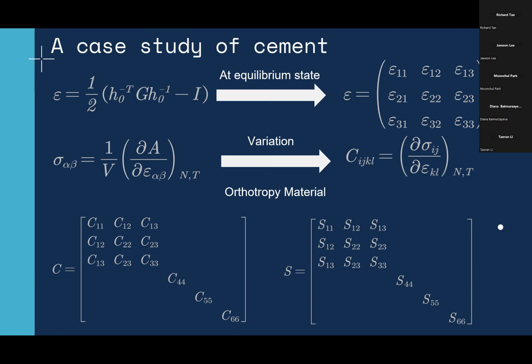And the strain tensor epsilon is associated with the stress tensor sigma. Together, they define the change in free energy of deformation. The stress tensor is obtained as the change in the free energy A with respect to the strain at a constant number of atoms and temperature.